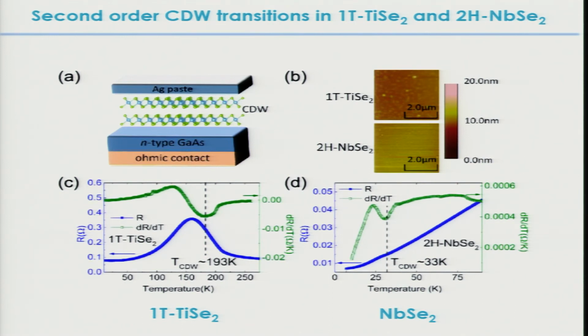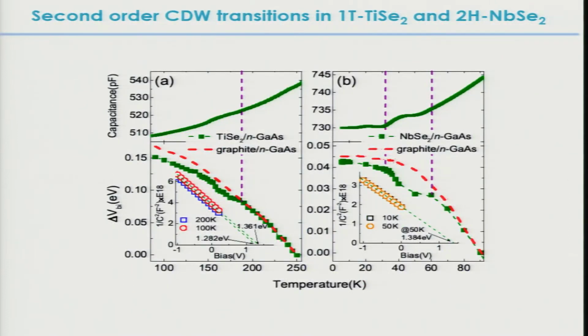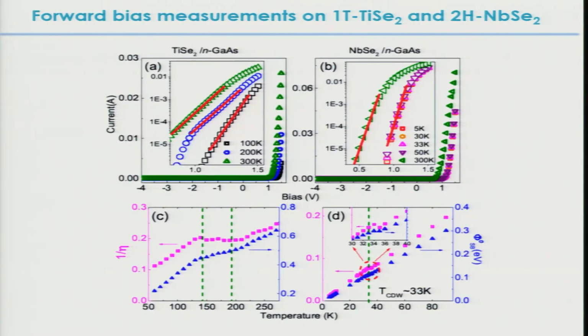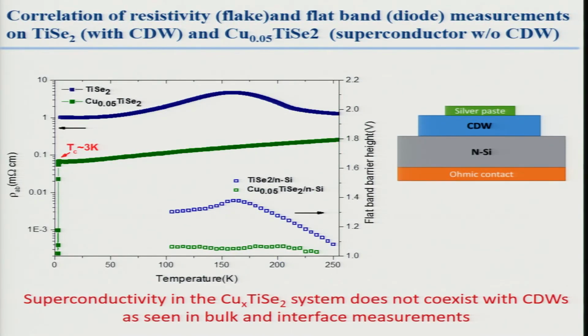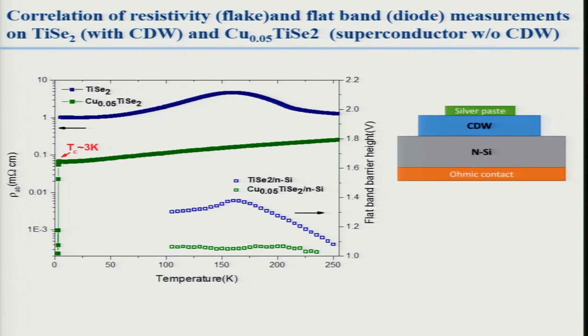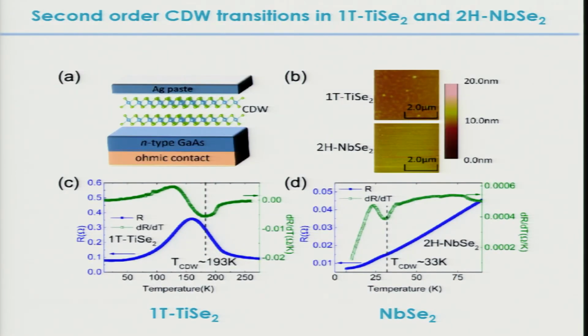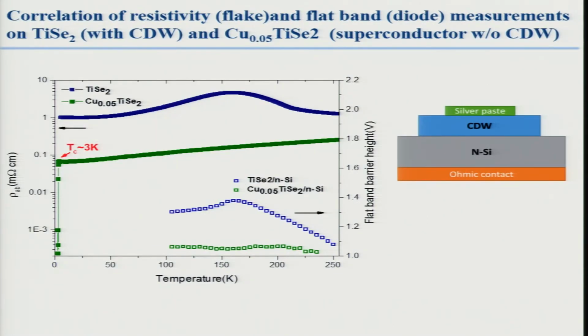And these are the resistance curves here. Let's see, the resistance curves. I'm going back. Here are the resistance curves. This is titanium diselenide, this is titanium diselenide, this is niobium diselenide. You can identify a CDW transition. We doped it with copper, and it becomes superconducting. Notice that when it becomes superconducting, the CDW disappears.